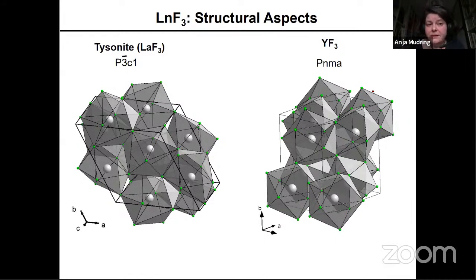The lanthanide fluorides are dimorphic. So you have the trigonal tysonite type shown on the left, and the orthorhombic yttrium trifluoride as two potential structure types. The local environment for the rare earth is the same, and that's why when we did our initial spectroscopic studies, we didn't see much, because with optical spectroscopy, you look at the first coordination shell, and that is similar. But the interatomic distance between the rare earth centers, shaded in gray, they are different. And since the whole concept of quantum cutting, so getting to a material that has 200% quantum yield, relies on energy exchange between two rare earth cations, the interatomic distance is quite critical.